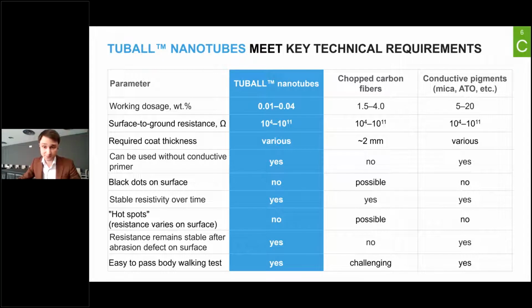Then the next point is that the level of conductivity, sometimes, in case of conductive range, the level of conductivity of the top coating is so high that you don't need to apply primers. I can tell you that many of my customers, in case of not very huge working surface area, are even not using primer, and they are applying the copper tape only at the perimeter of the object. So this, of course, helps to have some additional benefits from an economical point of view, because you use less material, you use less resources, and this is a much more sustainable solution.